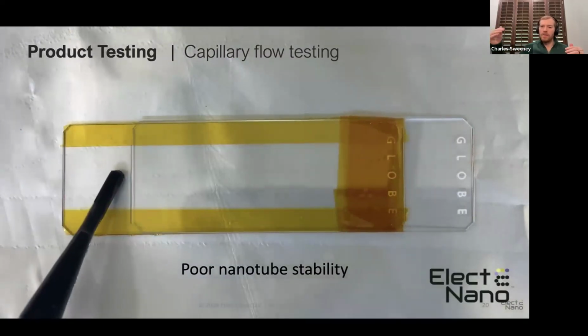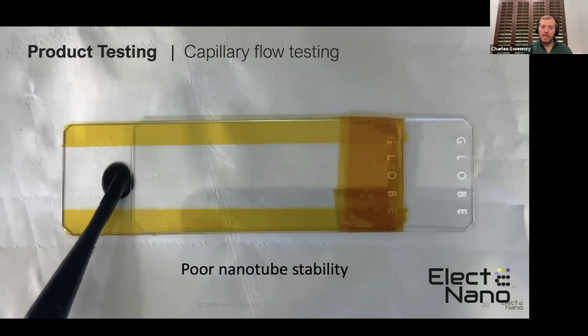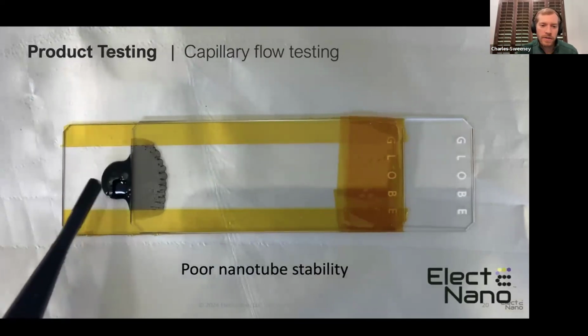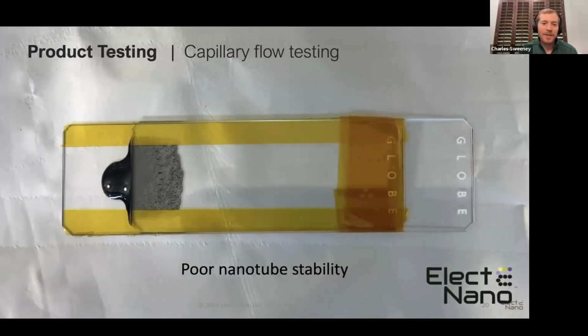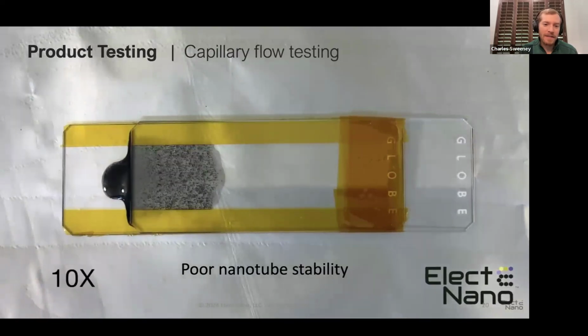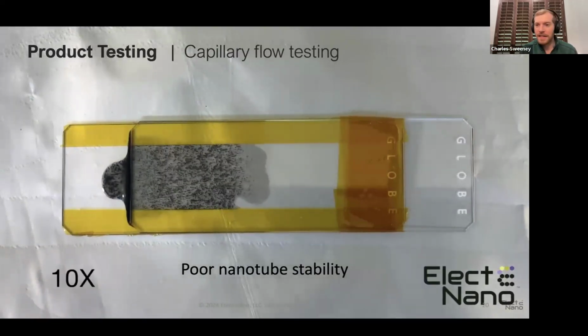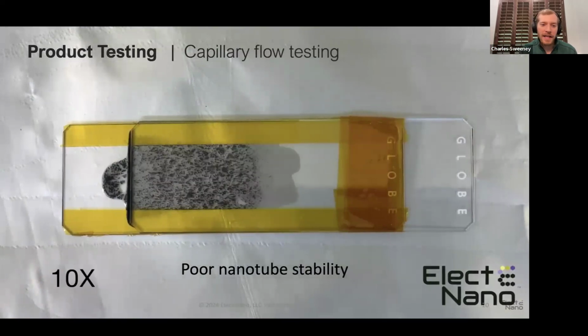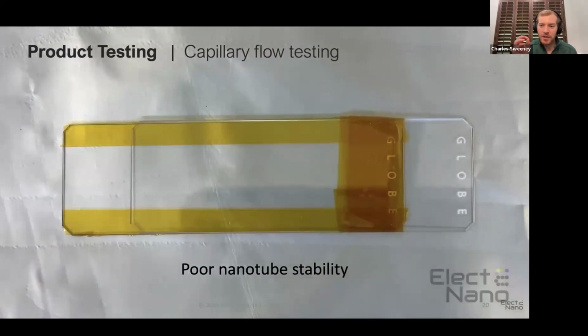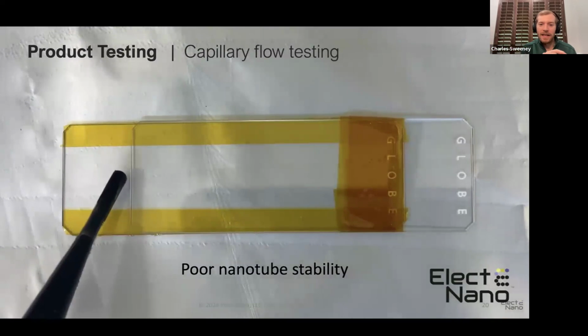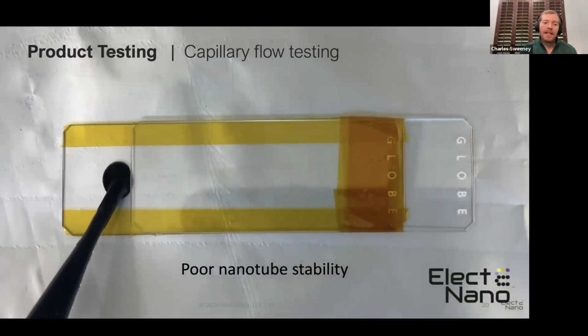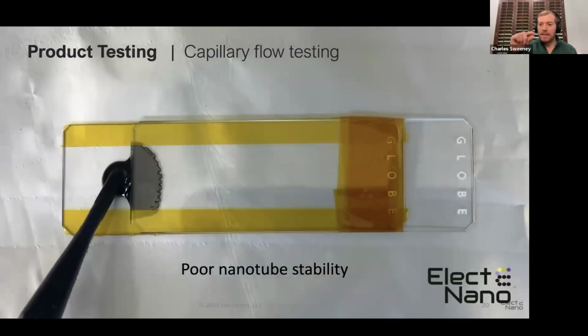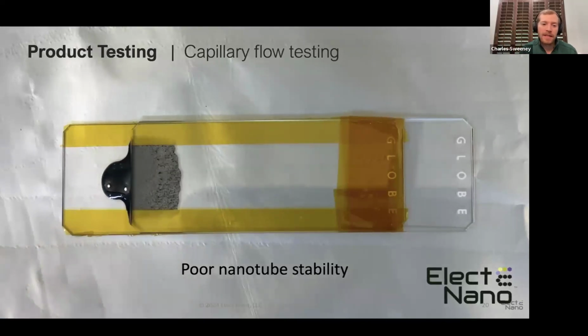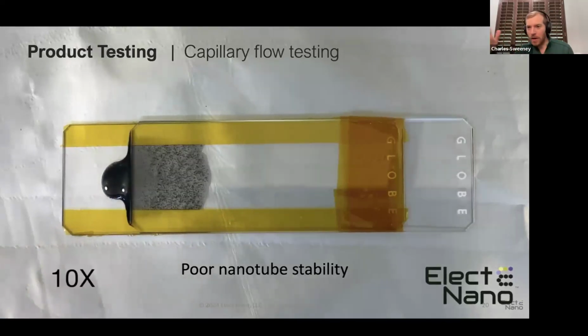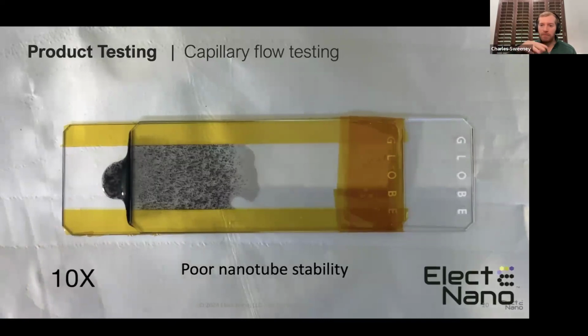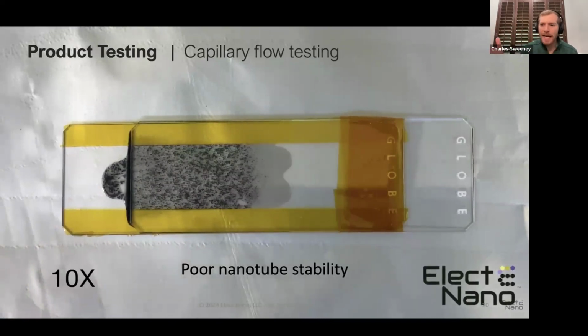You have to consider how the surface energy of the entire system is changing over the curing conditions. And so we got excited quickly, and then got not excited quickly when we found out that this is much harder than it looks: getting a good nanotube dispersion in a very thin capillary. This is two slides spaced out with a single layer of Kapton tape, and you're trying to get it to wick all the way across and not have any play out or wet out of the resin.